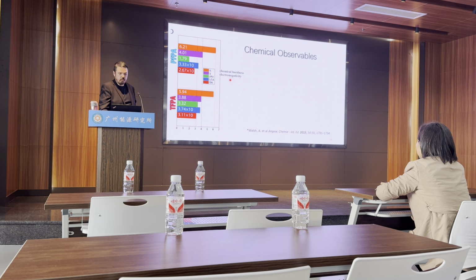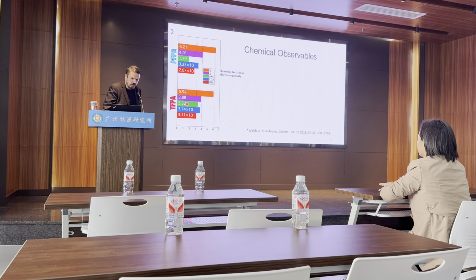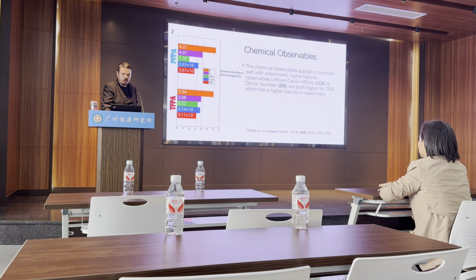So let's look at the chemical observables. Four of them are calculated. The green one is from the experiment, just for reference. This is chemical hardness, this is electronegativity. When we look at the lithium cation affinity and donor number, these are basicity observables. This is uncoordinated, this is coordinated. They're both higher for TFPA, which is good because our pKa goes up and our basicity observables go up. So everything's fine, everything's correct.